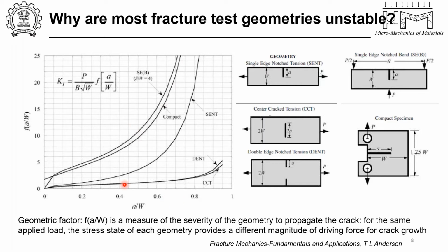This monotonic increase does not allow for the crack to arrest for a homogeneous monolithic specimen. That's not a problem if you want to just measure the initiation fracture toughness of a material, but you usually want to extract more out of a particular specimen, and that I will come to in a little while.